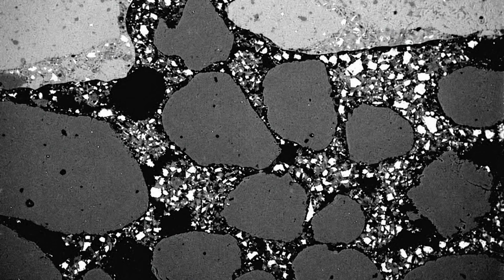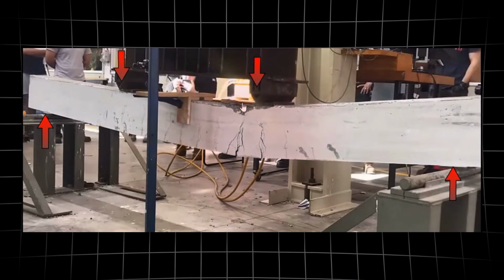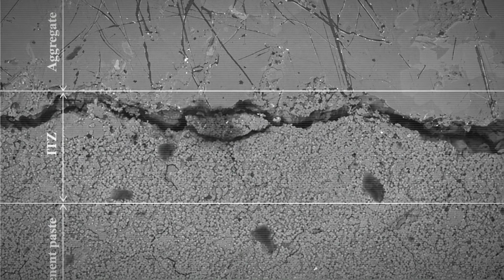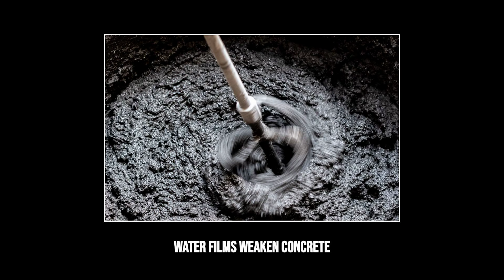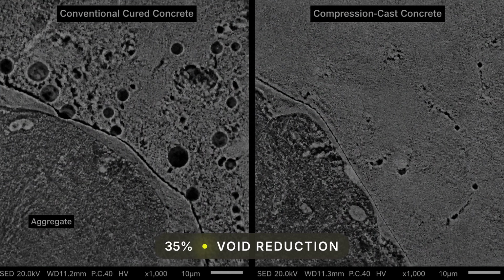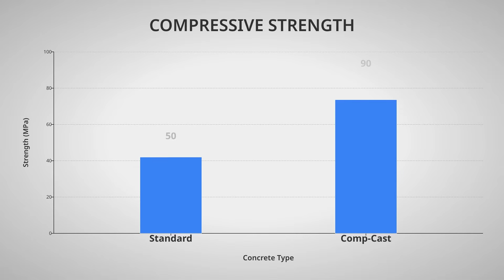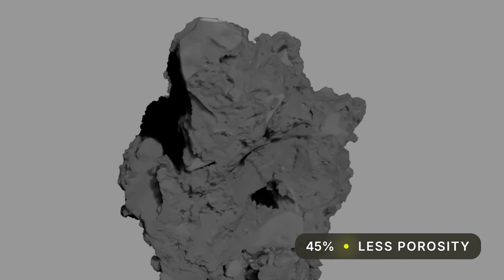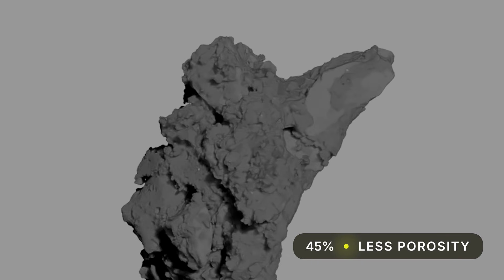Second, it collapses the interfacial transition zone, the boundary layer between cement paste and stone aggregate, historically the weakest point in any concrete structure. Under standard curing conditions, this zone has a higher void content than either the paste or the aggregate on their own, because water films form around aggregate particles during mixing and impede the tight packing of cement grains at the contact surface. Under compression, those voids collapse. The team's measurements showed a 35% reduction in void content at the transition zone compared to equivalent standard cured concrete. Total internal porosity across the sample fell by 45%.